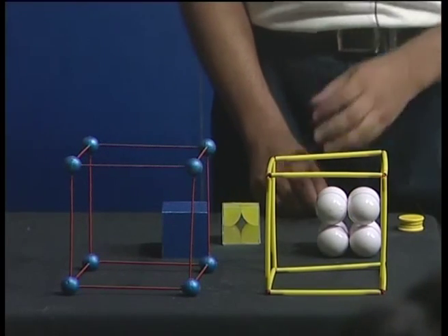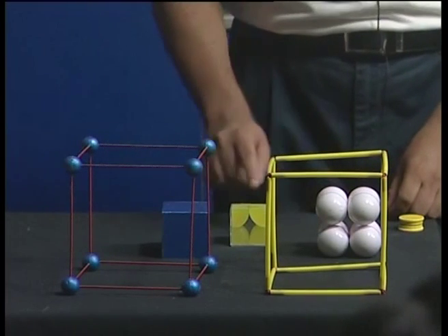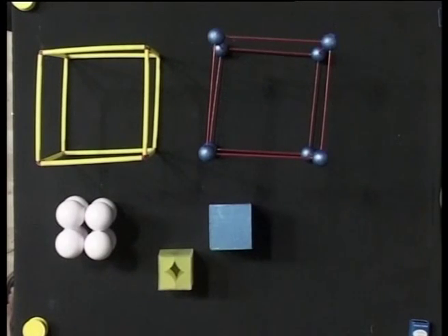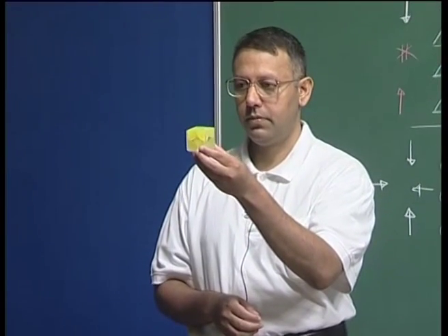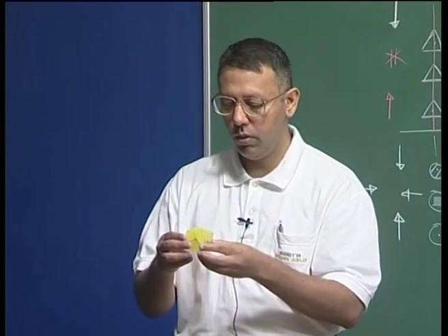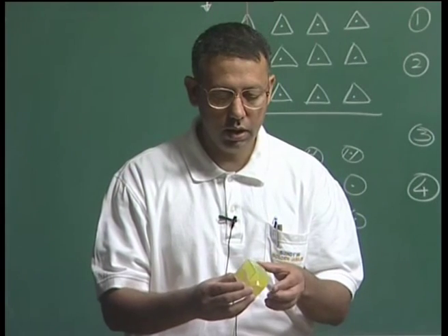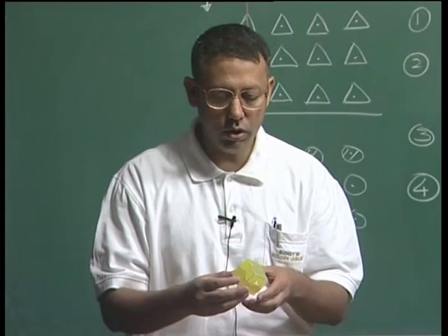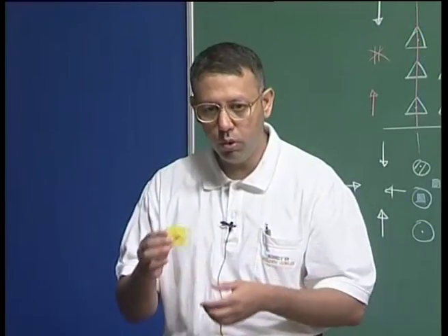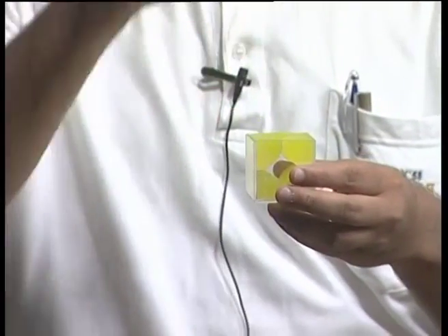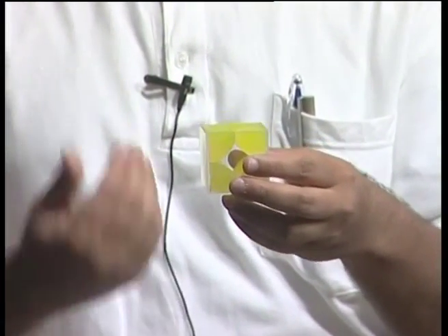For the simple cubic crystal, this is my unit cell, wherein there are 1/8 of atoms present at each lattice point. Okay. So I have cut my single sphere into 8 parts and I have put them on the 8 corners of this cube. So this is my model, wherein you can clearly see that now the atoms are 1/8 of the original sphere. So this is truly my unit cell, and when I put another unit cell next to it, and another next to it, and I do so in all 3 dimensions, I would get a crystal.